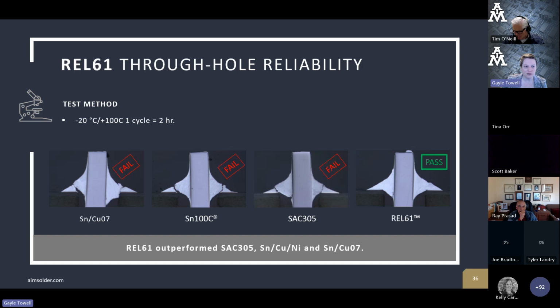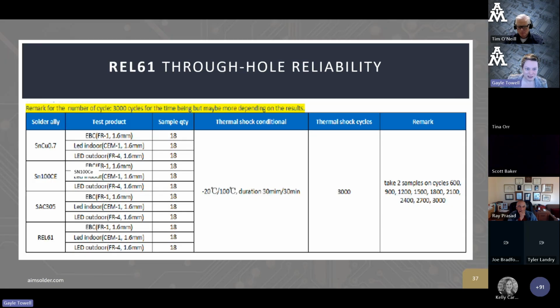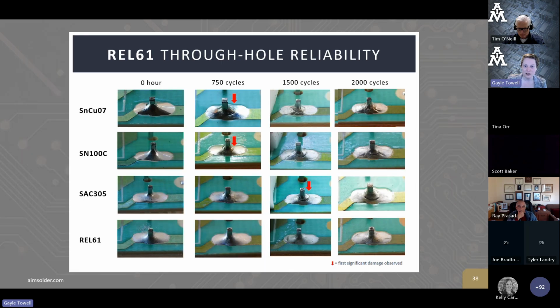This was some of the results of a thermal cycling test between -20 and 100 Celsius, looking at SAC305 compared to, sorry, REL61, SAC305, SN100C, and tin copper. This is a little hard to read, but it describes the thermal shock in the cycles, really thermal cycles, and how the test was run. But here's the real rub. These are the results. At 0 hours, no failures. At 750 cycles, we're starting to see failures with the tin copper and the SN100C. At 1500 cycles, we start seeing failures with SAC305. At 2000 cycles, REL61 is still holding strong and it's beating out all of them.